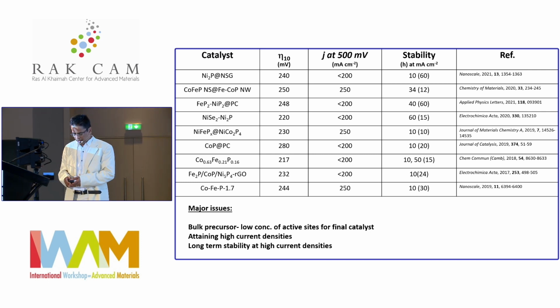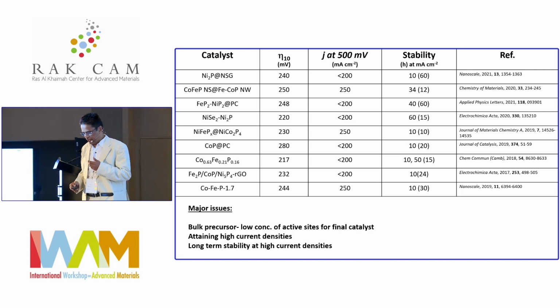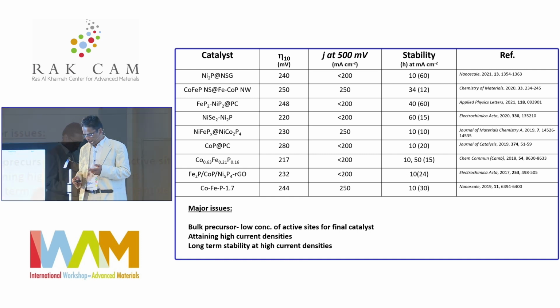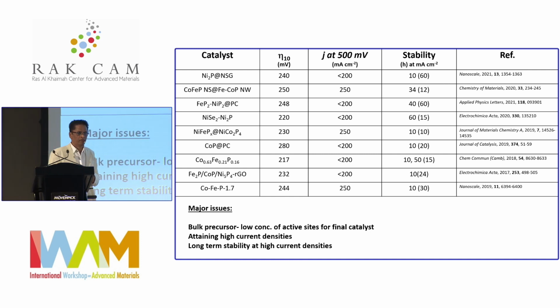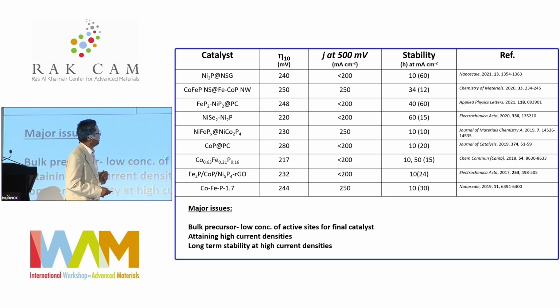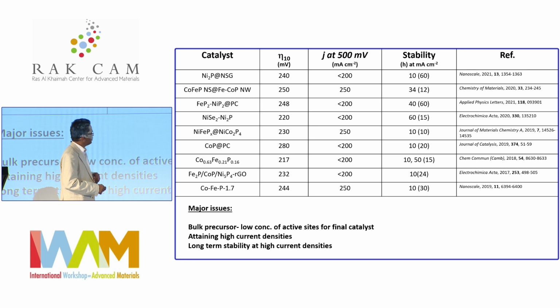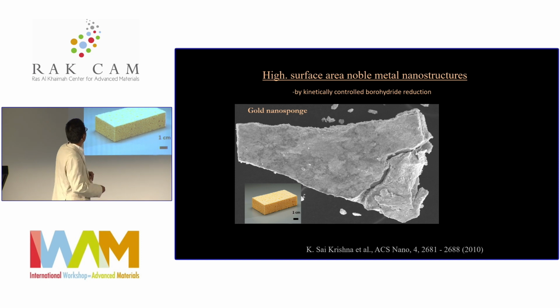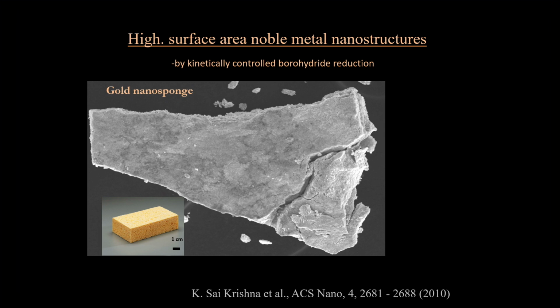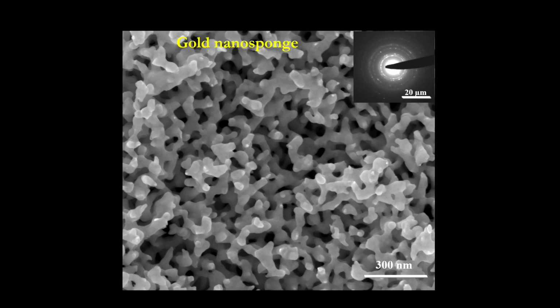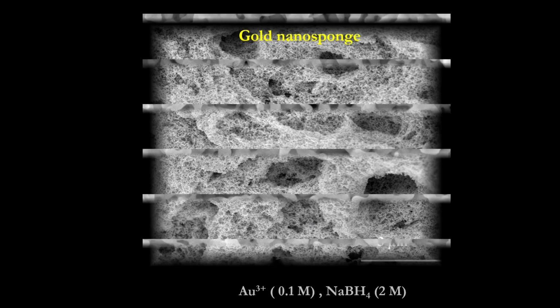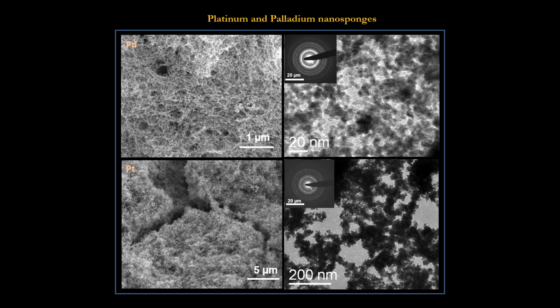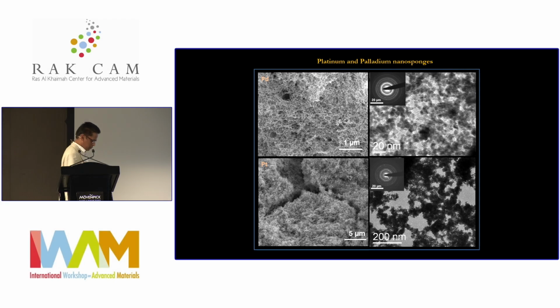So here we wanted to increase the active sites by making a high surface area precursor, prepared through the borohydride reduction of both cobalt and iron hydroxide. This strategy, which we used for preparation of metal nanostructures like gold, uses kinetically controlled nucleation to bring about porous nanostructures of gold, or even silver, platinum and palladium, which we wanted to use for this iron cobalt structure also.